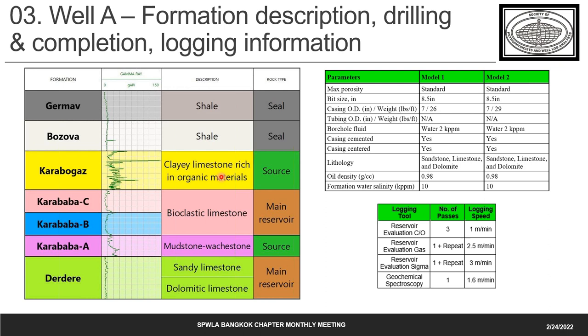This MCNP model helps us to quantify the oil saturation, of course, using also the porosity and the mineralogy from the geochemical logging tool. This is the saturation that was derived. And we identified some oil zones in the Karababa A formation, but also in the Karabogaz formation.